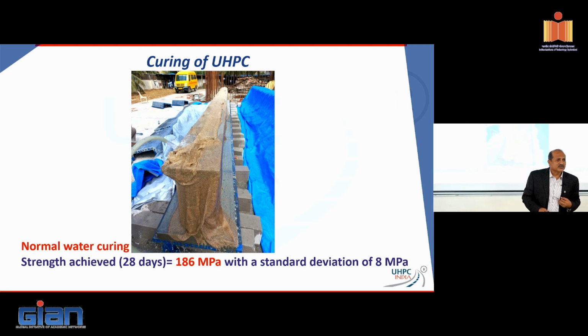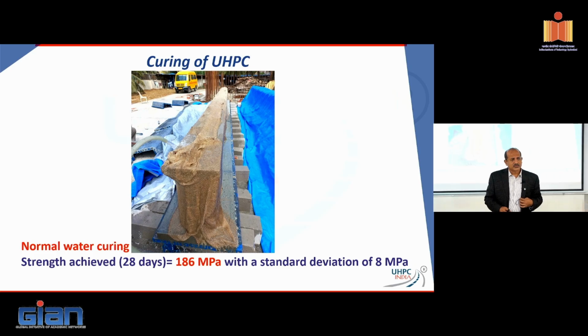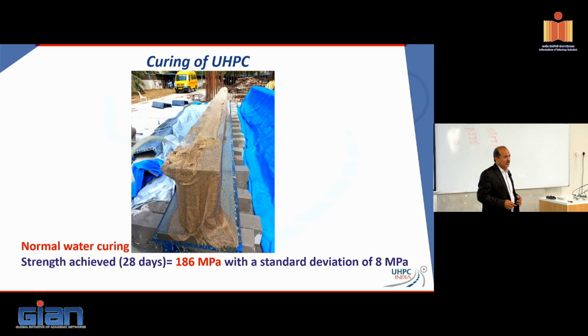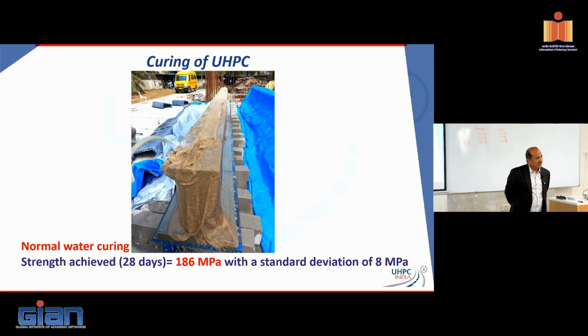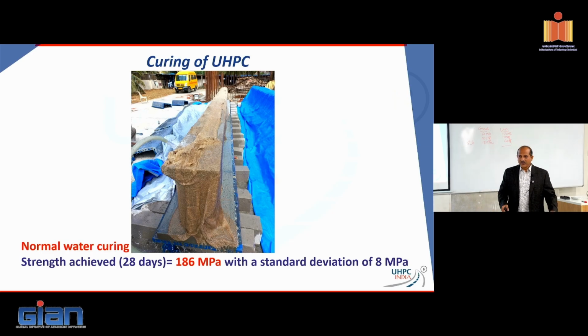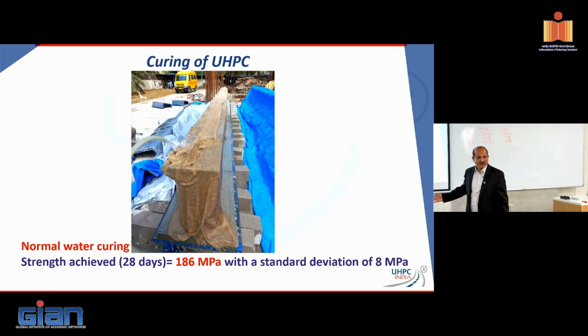If you want to develop a mix for 120, 150, 180 or 200, are there any standard ranges or standard deviation that I have to use? I think we are putting a number in the IRC right now. From whatever I'm collecting from Satyasilan and other data, the standard deviation is anywhere from 5 to 8, as you say. But again, the French code asks you to take 10 megapascal less than the characteristic strength. Yeah, 10, because you can easily reach that 9, 10. If we do it too tight, believe me, when you reject concrete you're going to be losing 7,000 rupees a cubic meter. For UHPC, you're going to be losing a lakh rupees a cubic meter. You cannot be that tight on it. When your base numbers are still matching, just because of standard deviation, you do not want to reject UHPC outright. Take a lower strength. Yeah.